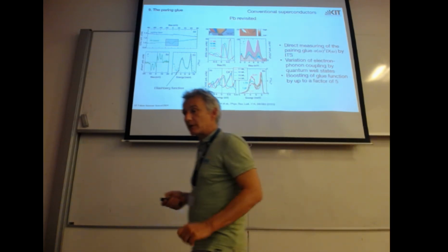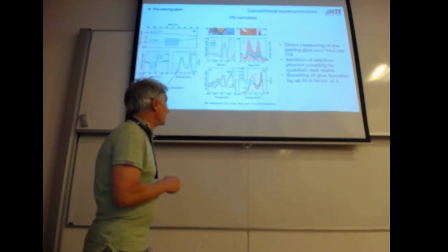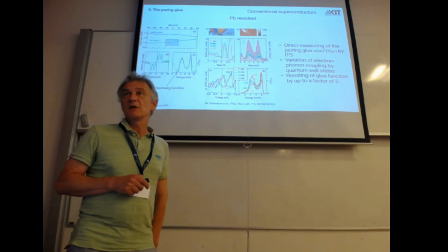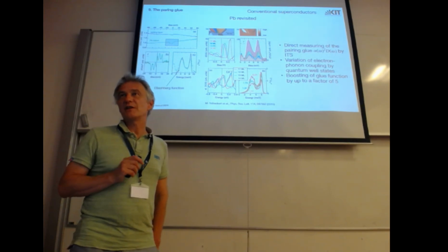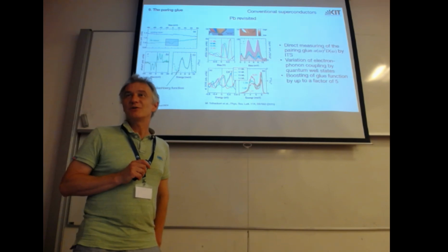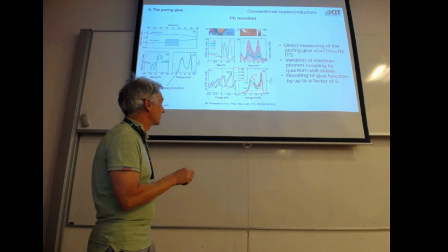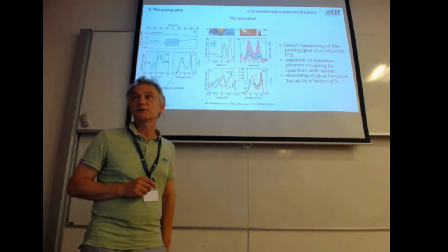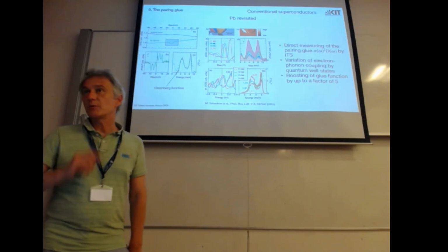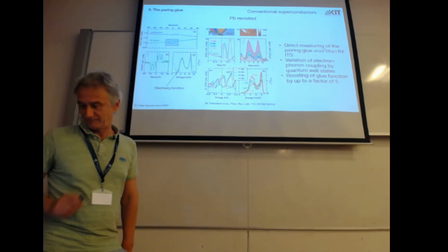We have an energy resolution of slightly below a milli-electron volt, and if you go to 4 Kelvin, then it will be more than a milli-electron volt. You wash this out. But you can suppress it with a magnetic field, of course.